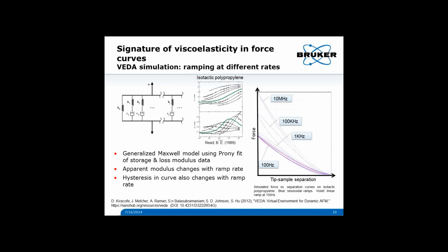Now, how should we analyze these force curves for viscoelasticity? We know that the hysteresis is related to the viscoelasticity, but it's not easily calculable because the deformation rate is changing during the ramp, and this happens because the contact area is changing. This is kind of a known problem with indentation type measurements.